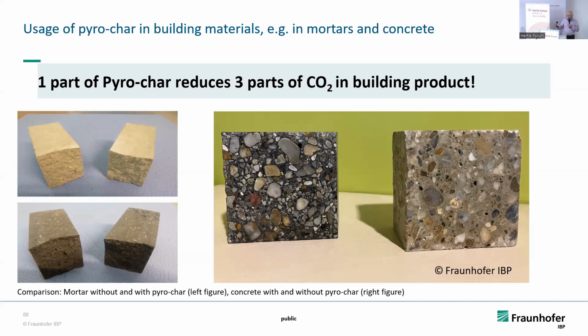But we wanted to go a step further. We found a method to granulate this pyrochar, so now we can get a particle size distribution. And here you see, for example, the approach. We replace the sand fraction smaller than 2 millimeters with this granulated pyrochar, and it still works. So the concrete has the same mechanical properties. We were also surprised, but it's lighter than normal concrete, because if you replace gravel, quartz, with pyrochar, it's much lighter. And I think it's even much prettier than the normal concrete. So yes, we're still not at the end of the road here. I think there are still some open questions. Maybe in the future we can even replace big gravel with these pyrochar granulates.